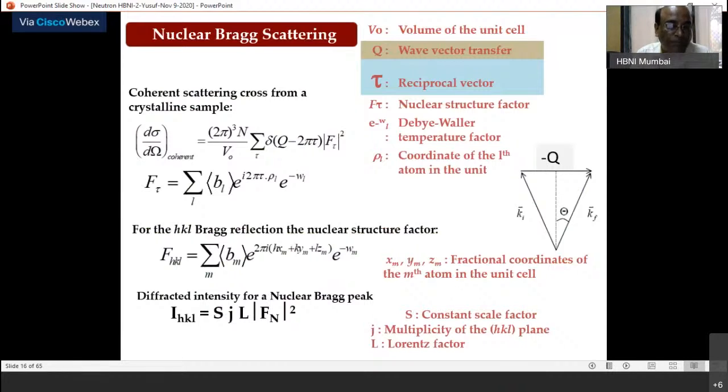Okay, that is the way it is done, right? But what you lose is the intensity. So that means the S factor will change. That means, depending upon the instrument configuration, the collimation. You can also imagine you are changing the sample. If I do an experiment today for the same compound with, let us say, 1 gram, and tomorrow I do it with 3 grams, the number of scatterers put in the beam is different. So that all will lead to a different scale factor.